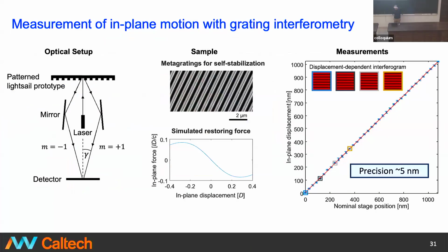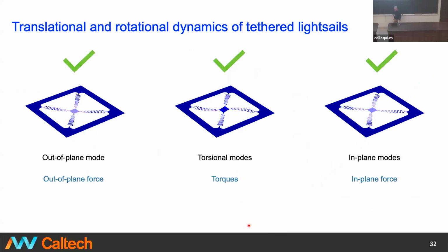Everything I told you so far was about out of plane motion, but I'm also interested in learning what the in plane motion is in response to the structures that I've created. Fortunately, the metagratings themselves can also be used to create an interferogram that produces a displacement dependent interferometric measurement. We can use that in this reflection configuration to determine the position in the lateral direction with a precision of about 5 nanometers. So we have about 5 to 10 picometers resolution out of plane and 5 to 10 nanometers in plane. Now we were able to determine the dynamics of the light sail.